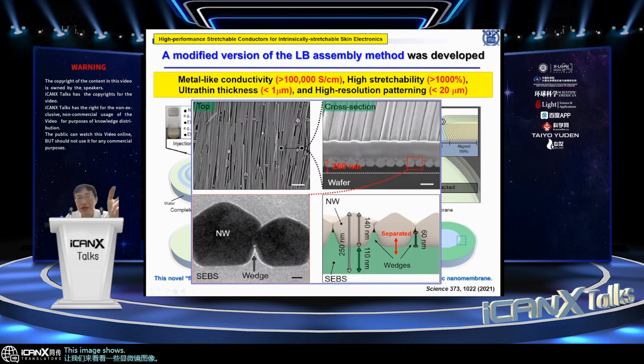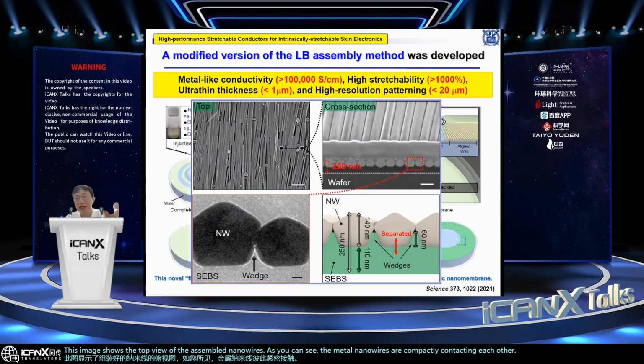This image shows the top view of the assembled nanowires. As you can see, metal nanowires are compactly contacted each other. As I mentioned, usually the intrinsic conductivity of silver nanowire is very, very high, but the problem is that the contact resistance can be high if the contact between nanowires is not good. But in this case, as you can see, individual nanowires are well contacted to each other. So we have very large contact area. Therefore, contact resistance can be minimized. Therefore, metal-like conductivity, like 100,000 Siemens per centimeter or 150,000 Siemens per centimeter could be achieved.